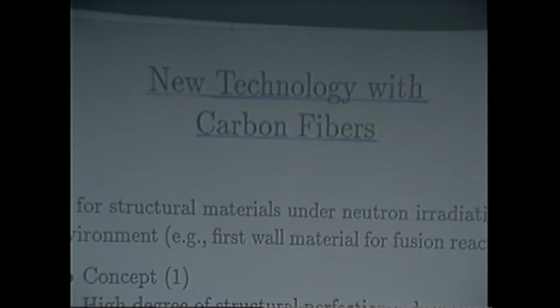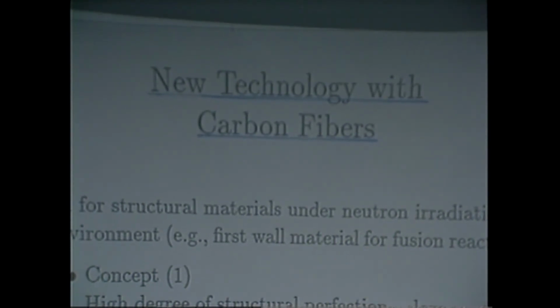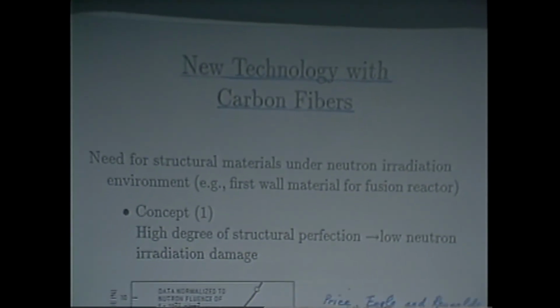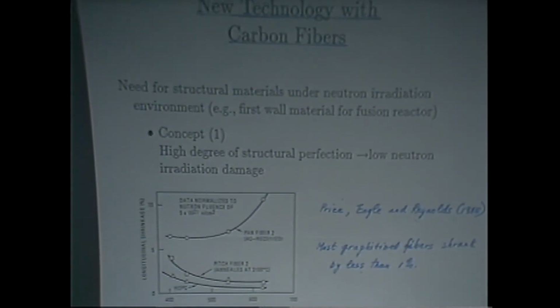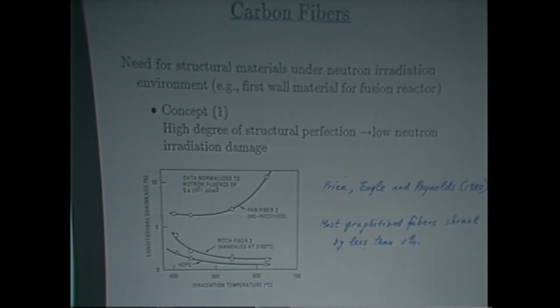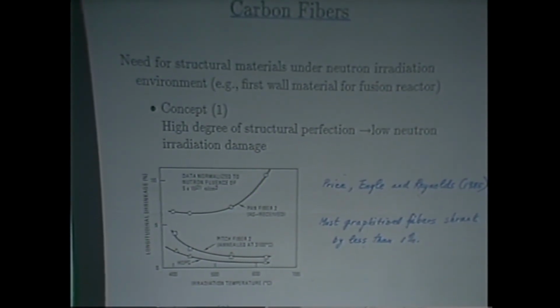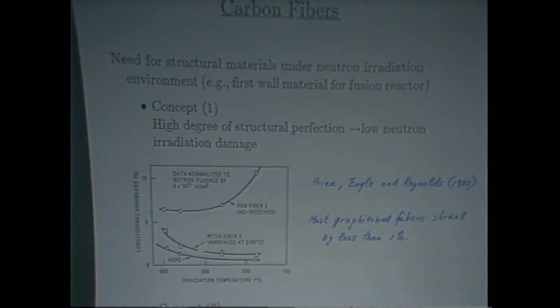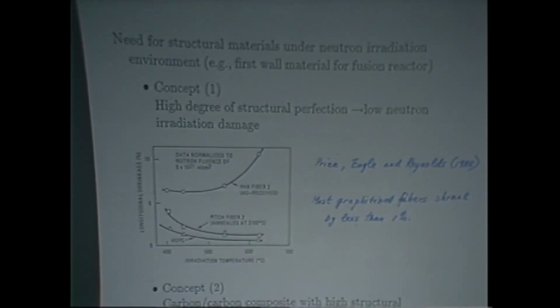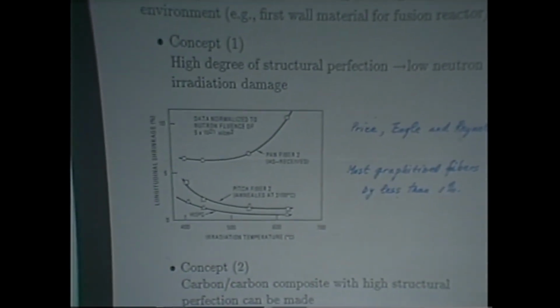New technology. I hope that there's somebody from plasma physics here, because this is one of the interesting areas for this particular application of carbon fibers. I suggested to somebody that because these carbon fibers can be made so perfect, maybe you could use them in a neutron environment because they would be radiation hard. I made that suggestion to some people at GA Technology where they do these kinds of measurements, and they took the fibers that I gave them and they tried them out in the reactor at Oak Ridge. And lo and behold, it really worked out that there was almost no shrinkage of these highly graphitic materials, that crystalline order prevents